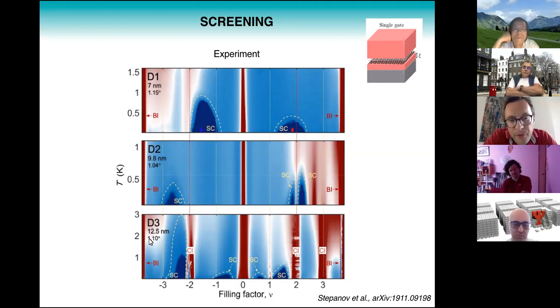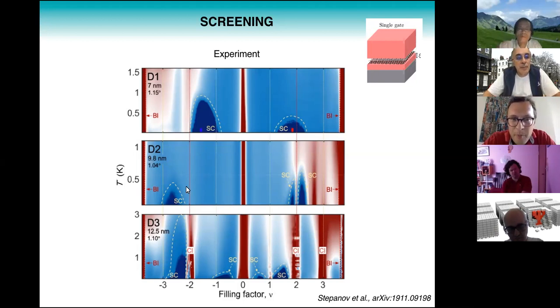Now, for the thick boron nitride layer, which is device D3, you get a phase diagram that looks very much like the one we've seen before, where you get multiple correlated insulator states at integer fillings, and then between these correlated insulator states, there are a bunch of superconducting domes. But you see that the phase diagram changes quite dramatically as you go to a spacer layer of only 10 nanometer thickness. You see some of these correlated insulator states start to disappear. And finally, as you go to 7 nanometers, almost all of them have disappeared. So there's a bit of a signature here.